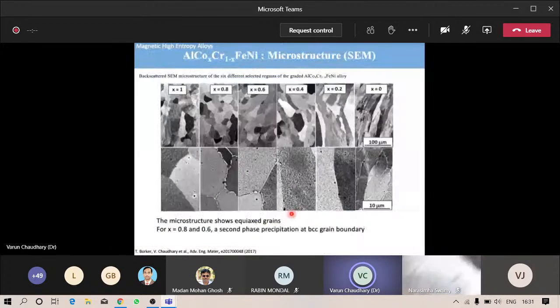These are the back-scattered SEM microstructures for all these samples, x equal to 1, 0.8, 0.6, 0.4, and x equal to 0. You see all these microstructures are equiaxed grains. But for x equal to 0.8 and x equal to 0.6, there is some precipitate phase at the grain boundary.